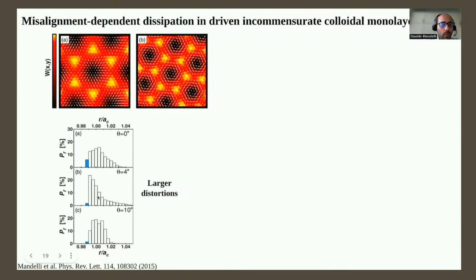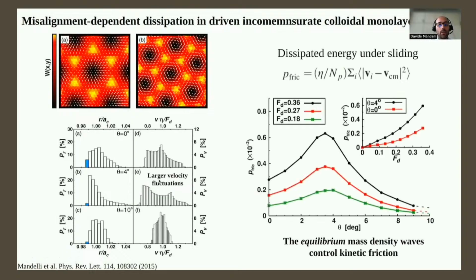What I'm showing in this plot is the distribution of the interparticle distance within the layer for different misalignment angles. As you can see, the distribution becomes broader as we approach the equilibrium optimal angle, shown here in the middle, and then shrinks again. Now, upon sliding, this mass density wave propagates within the monolayer, and large distortion upon sliding leads to larger velocity fluctuation of the internal velocities of the particles.